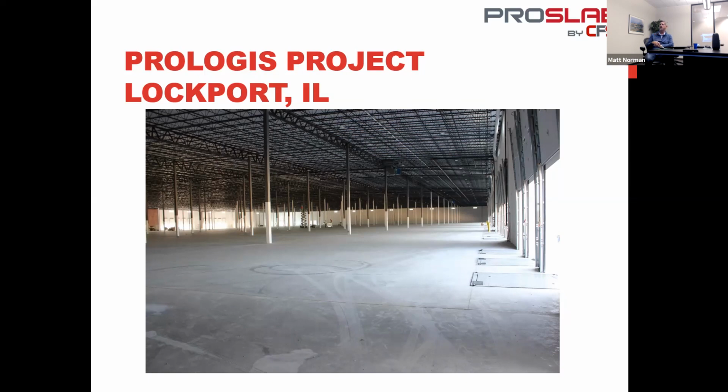delay the fill process of the joints as long as you potentially can. As we know, a slab shrinks for a long time. An 8-inch slab can shrink for up to 2 years. Now, obviously, the majority of the shrinkage occurs within the first 90 to 120 to 200 days, but there is still minimal shrinkage further out. If you can delay your joint filling as long as you can, then it will allow for the potential to maybe not readdress that joint fill a year down the road.